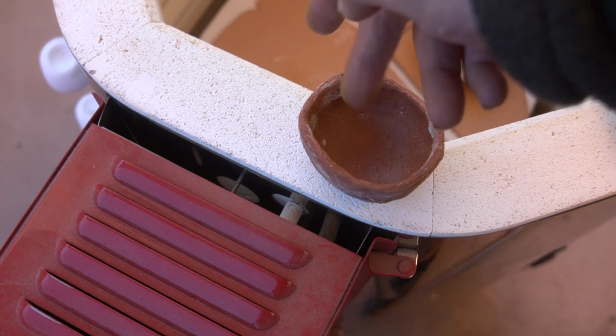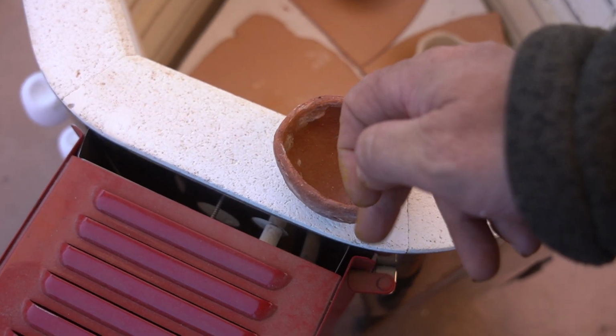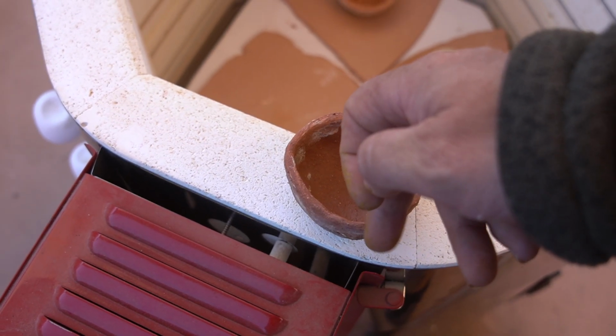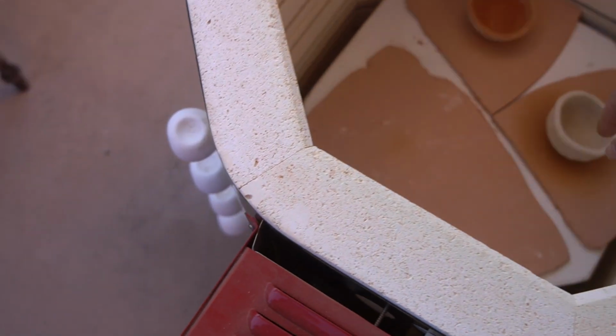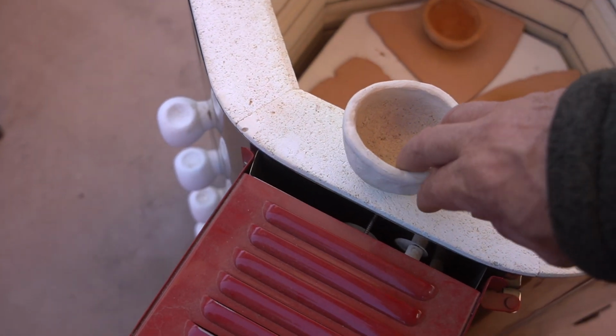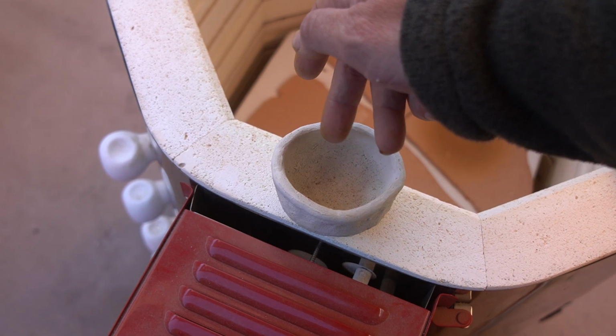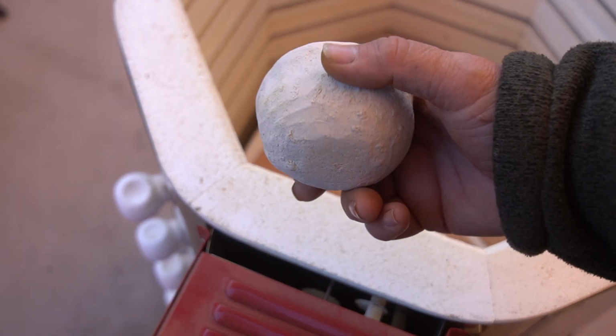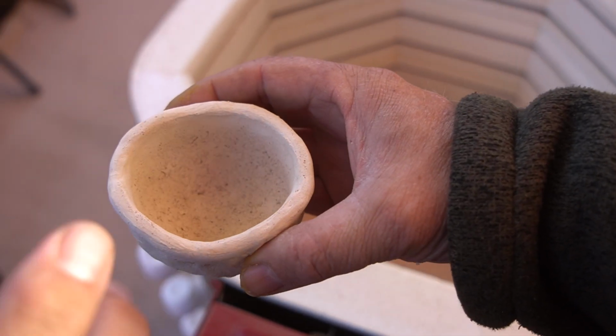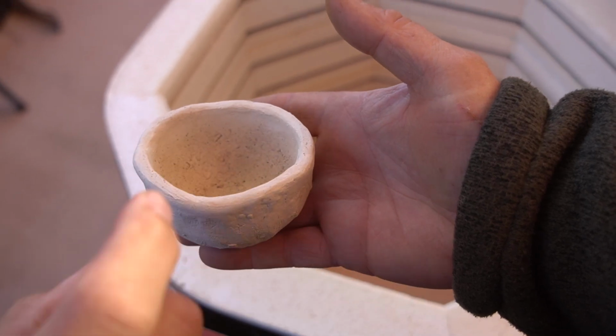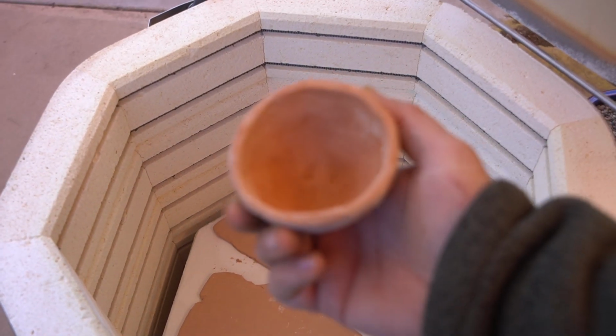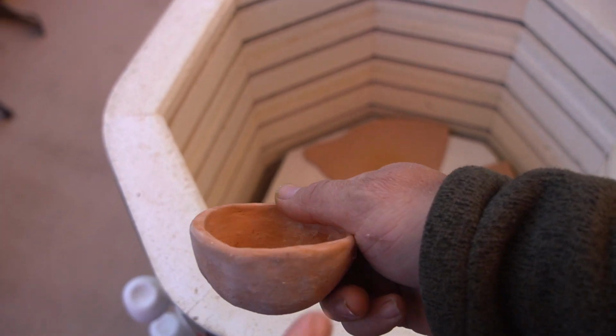So in firing these pots to over 1000 degrees Celsius, I thought for sure at least one of those clays was going to melt. Specifically that old Sonoyta Highway Red. I've misfired that a number of times in outdoor firings where wind came up on my fire and the temperature got way over 900 degrees Celsius, and I had some strange results which looked like overfiring. But in this case, they fired to over 1,000 degrees Celsius and there seemed to be nothing wrong with them.